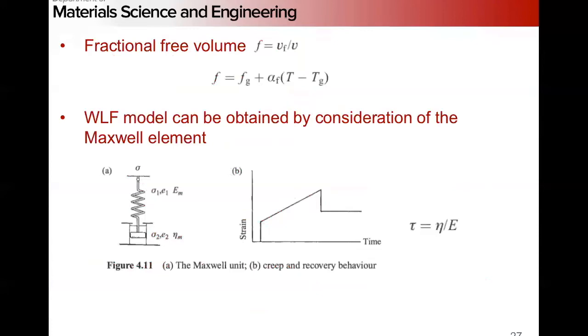Right. So if we consider a fractional free volume, this is the free volume over the total volume. We can define that as the fraction at the glass transition plus a linear term, which is the difference between the current temperature and the TG. This is essentially very much like a thermal expansion coefficient.